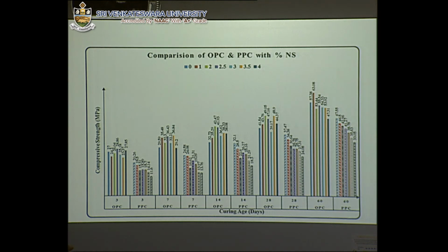In the case of OPC, we get a high compressive strength of 63.108 MPa, whereas in PPC, because fly ash of more than 10% is already given, SiO2 is already available in the fly ash. If you add another SiO2, the available calcium hydroxide, the pozzolanic effect, will not utilize it, and that is the reason adding nano silica is not useful in the case of PPC, and the strength is reduced. We have the different concentrations.